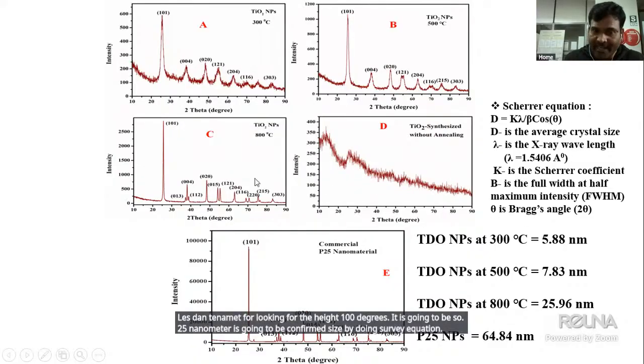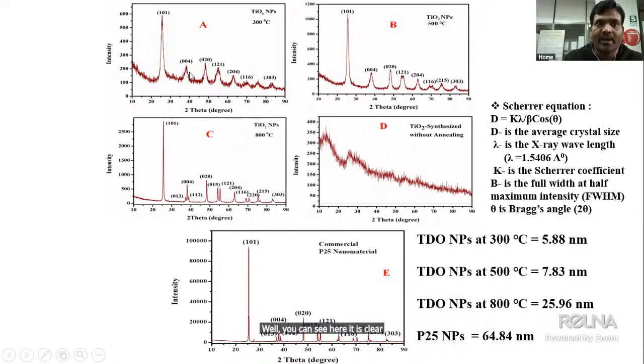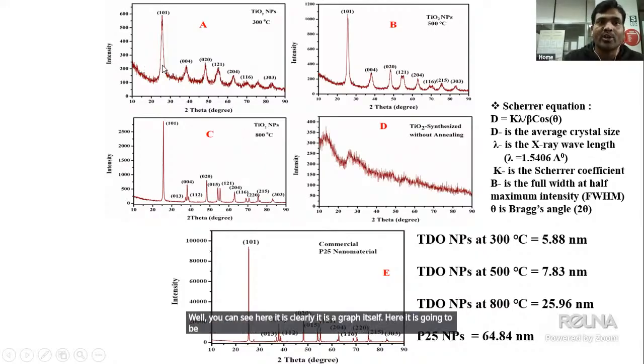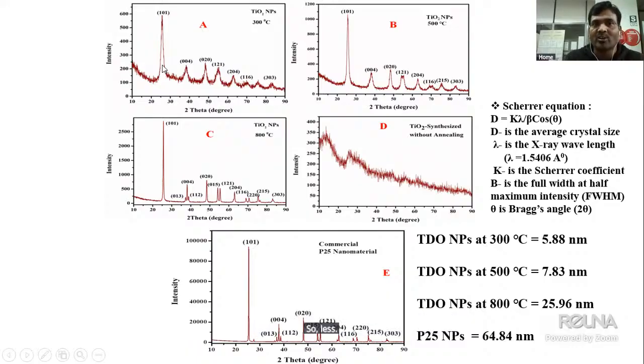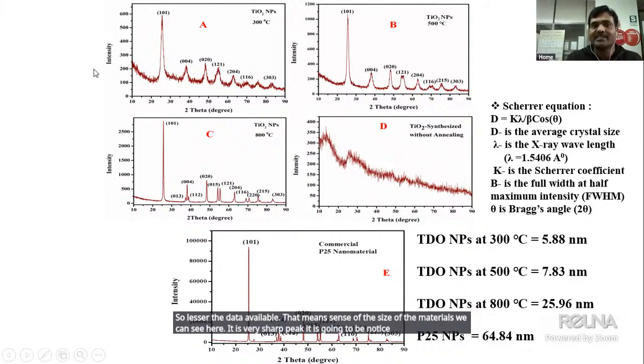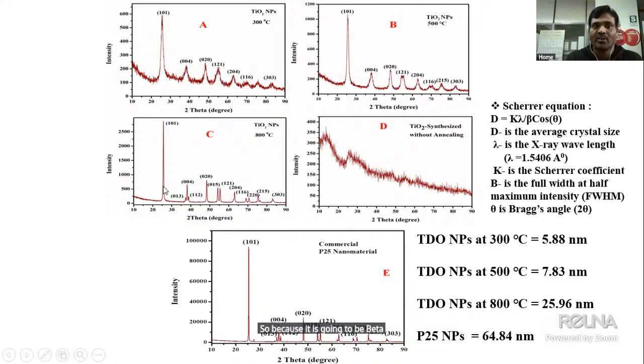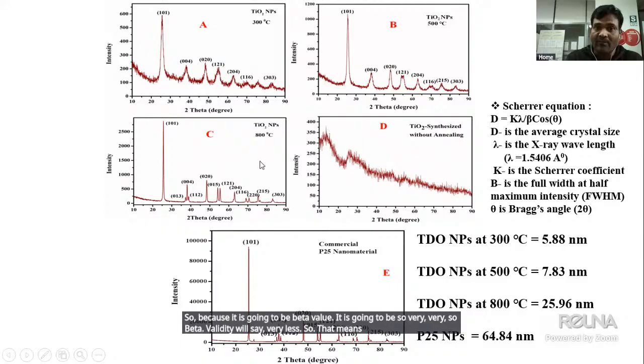You can see here clearly, the graph itself shows it. Here the beta value is less. The lesser the beta value, that means the size of the material is larger; we can see a very sharp peak, which is noticed with the higher size of the material, because the beta value is very less. So the graph itself shows which material it is, and the smaller size of the material is confirmed by the XRD analysis.